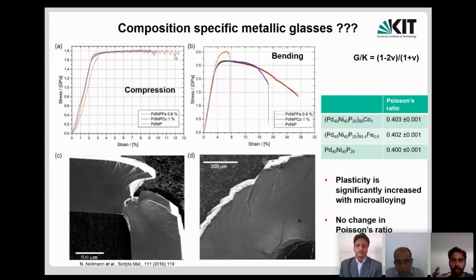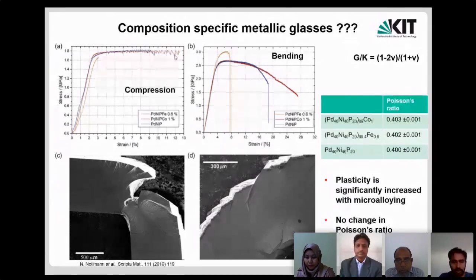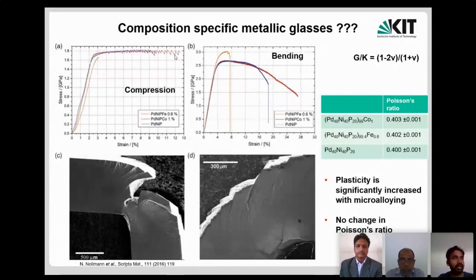So when you have that high cooling rate, you can imagine that if you have a cylindrical die, the surface of the die would give you more cooling rate, but the interior of the rod or whatever you want to cast will have less. So you can have a glass at the surface, and you can have a crystal at the center, which may not help. So the problem is producing them on a bulk scale is not easy, and the other problem is the fatigue properties of these are also not very clear, or not great in some cases, although they have some ductility. So I would probably use them as some kind of functional application, like these biomedical devices or some kind of resistance heat patches recently people are developing. So that kind of thing I would use, yes.